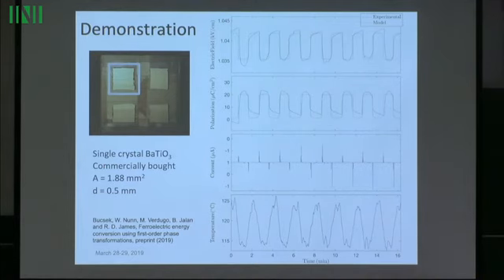And sure enough, it works quite nicely. In this demonstration, this is a single crystal of barium titanate. It has two electrodes on it. It was just bought commercially, and then it was heated and cooled on a hot plate. And you can see that this is the electric field according to the model, as well as measured in the experiment. This is the polarization from the model and the experiment. And this is the generation of electricity. Each time you go through the phase transformation, heating or cooling, and this is the temperature, you get a pulse of current.